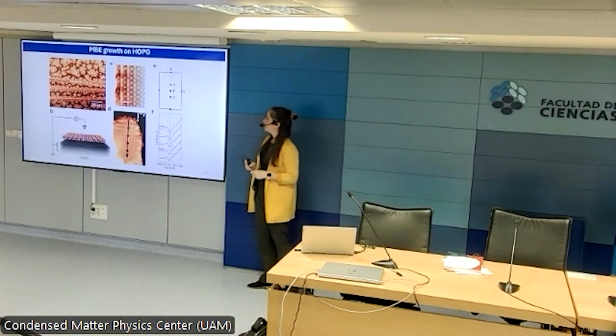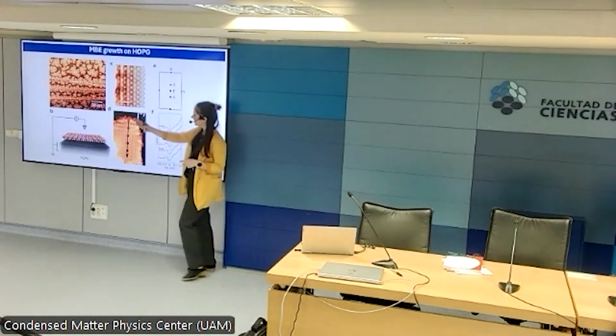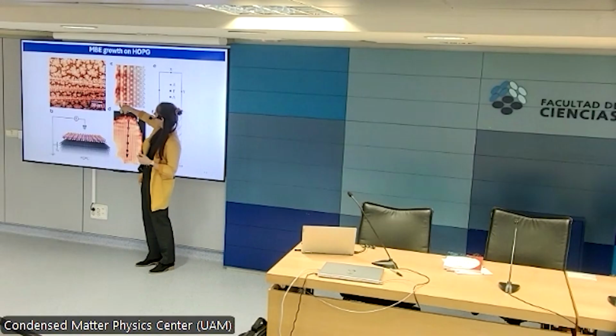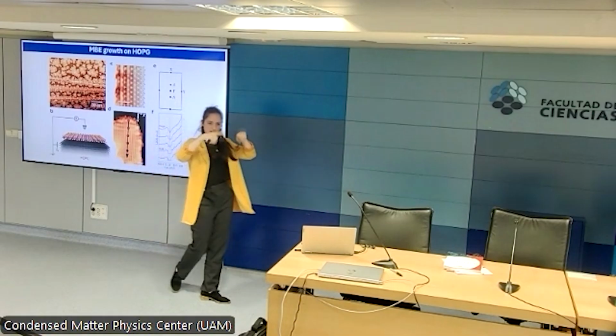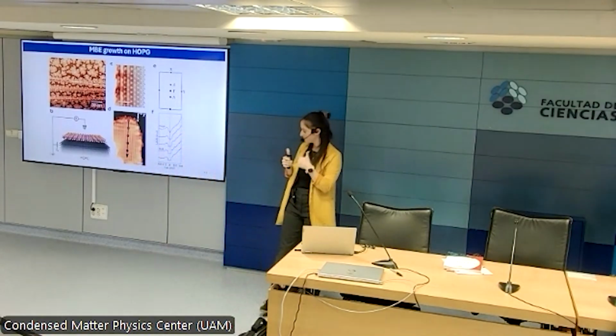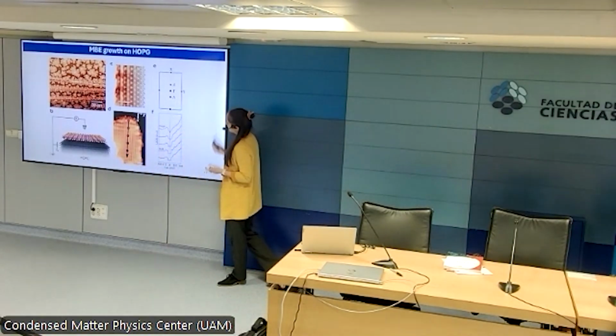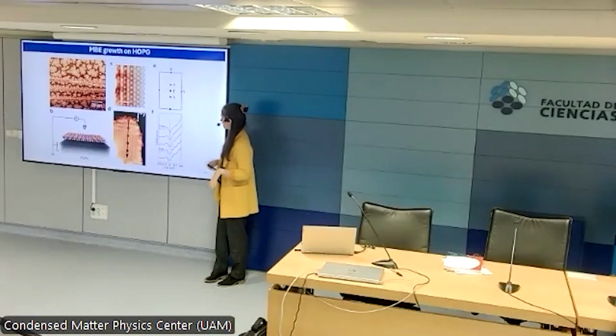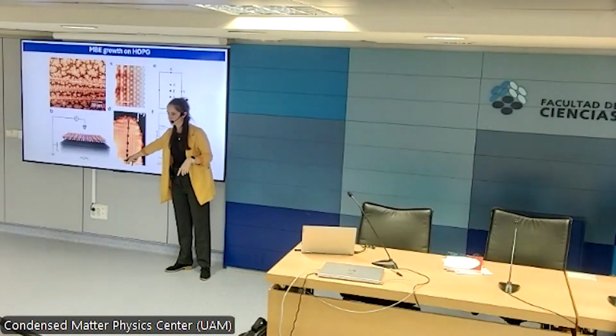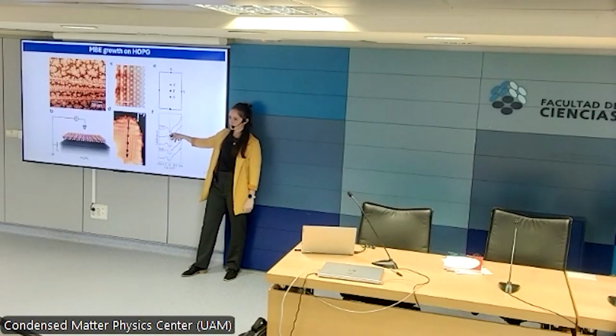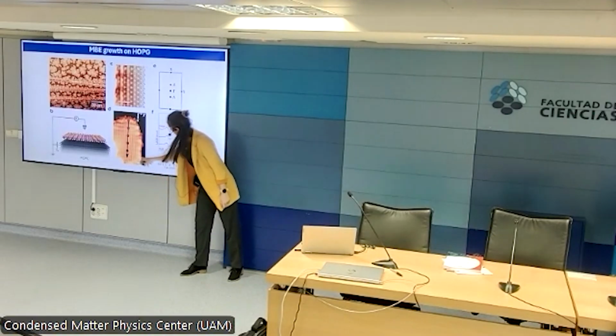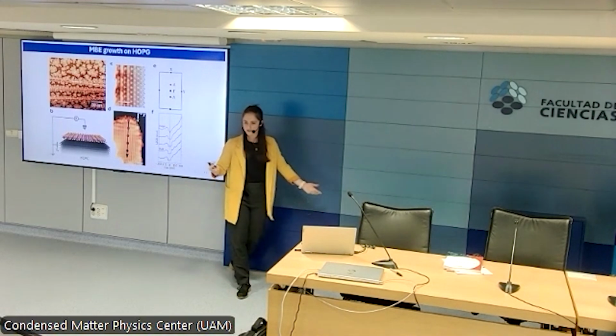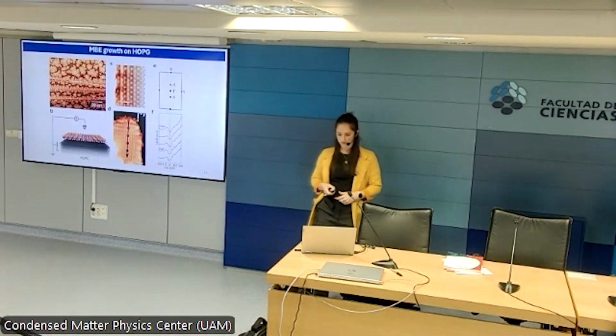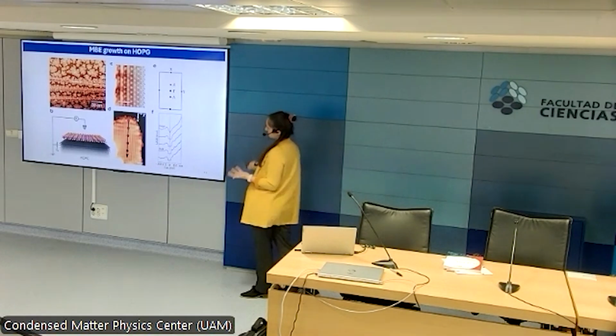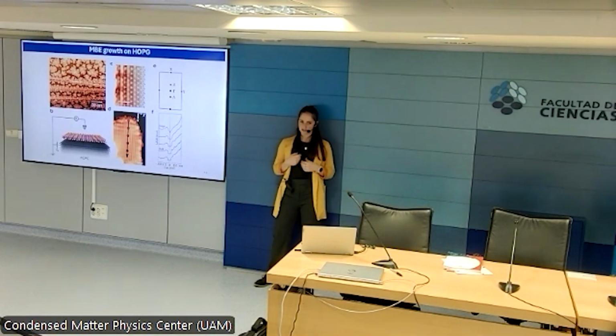Let's check that this is actually tungsten ditelluride in the structure we want. We zoom up in atomic resolution image. You can see that there are rows that are bright and dark alternating, which are the chalcogens up and downs that I was mentioning to you at the beginning, so check. The first thing we want to check is that actually we are in a topological insulator configuration. So we look at the density of states going from the edge towards the bulk. At the edge, we see a V-shaped density of states, that's a metal. In the bulk, we see a hard band gap of about 60 meV, that's an insulator, so that's a topological insulator there, check.